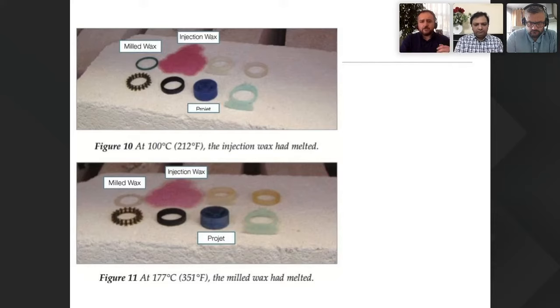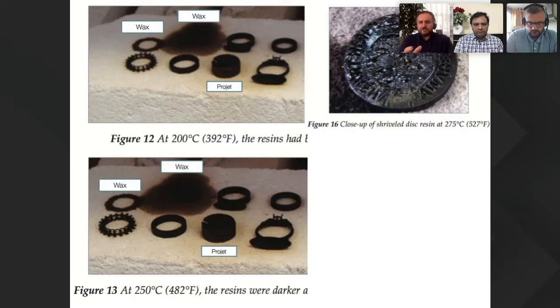Let's increase the heat a bit more. At 200 degrees, okay, we don't see anything about wax. There's still a black spot there, but the resins and the ProJet part—what you can see is they become dark, a sort of carbonification. So you can see that something has happened at 200 to 250 degrees.